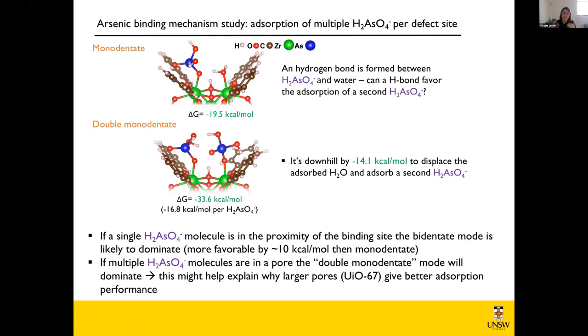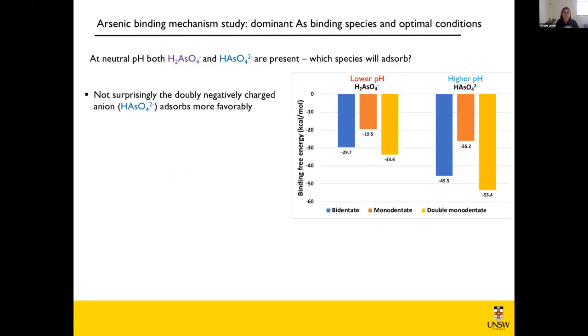It might not just be about diffusion, it might be about the size of the pores allowing more molecules to be in the vicinity of the defect site. And obviously these two things are interconnected. So we then did a similar analysis for the other arsenic species, the hydrogen arsenate. I'm not going to go too much into details, but I have a summary here for you. The first thing you can see is that the doubly deprotonated anion has a much stronger binding energy, which is not surprising.